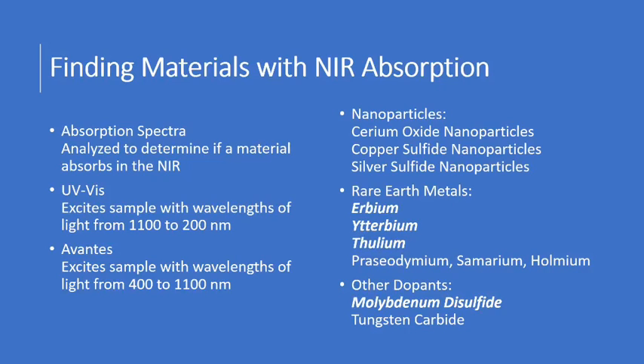And then the other dopants we looked at were molybdenum disulfide and tungsten carbide. Both of these are hard to dissolve in water, and it's important that they're dissolved in water because of how we make them. I'll explain more of that in a minute, but tungsten carbide we could not get to dissolve at all, and so we couldn't use that even though it has good absorption in the near-infrared.